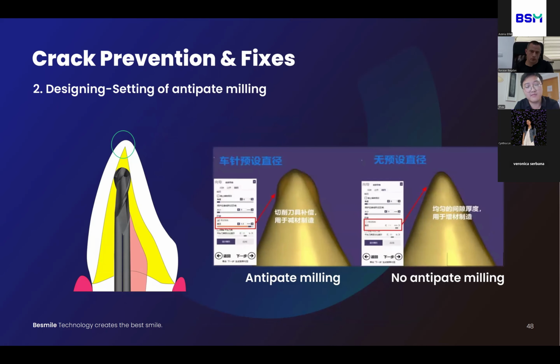Okay, and when we design, in the designing software, there's a parameter called antipate milling. So we also need to check if this parameter is set correctly. Generally, the value of the antipate milling should be more than 1 millimeter. So we recommend the value is like 1.1 or 1.2 millimeters to ensure the designed crown has no sharp cavity, to make sure the mini burr can mill out the incisor part.